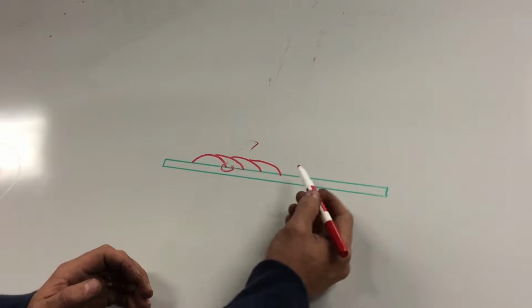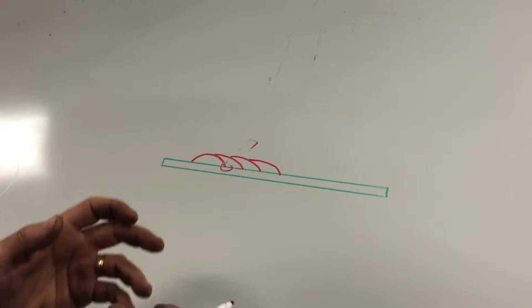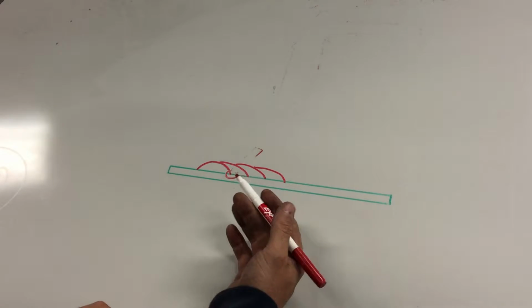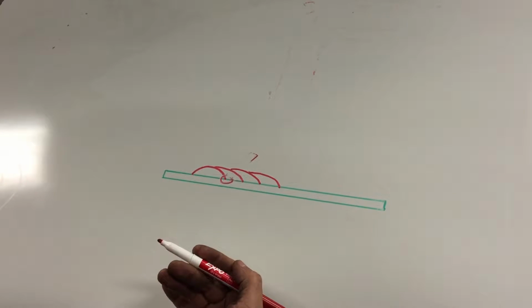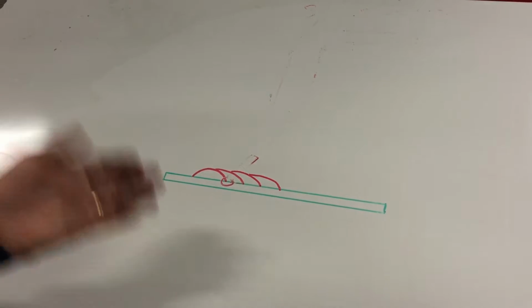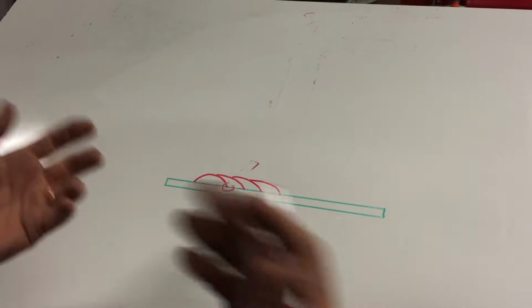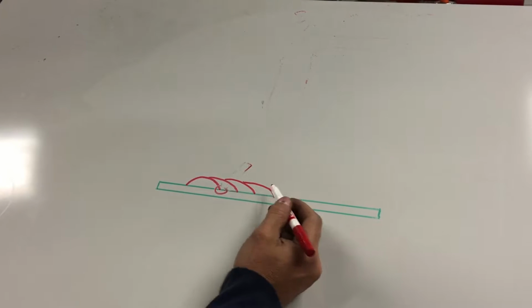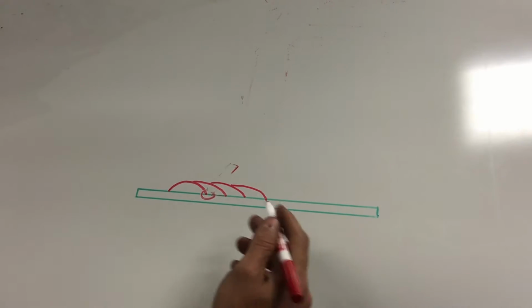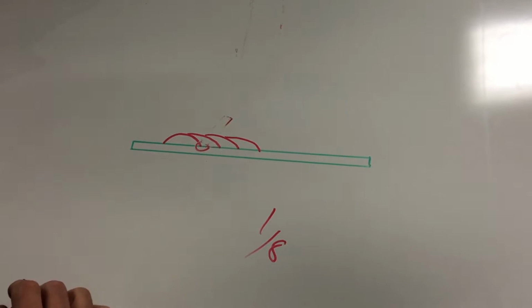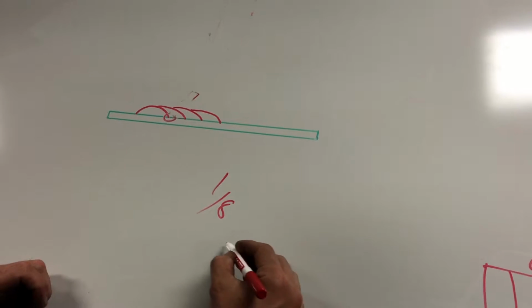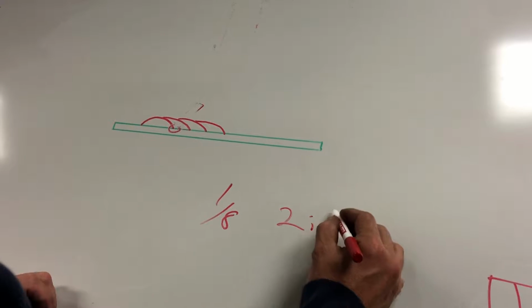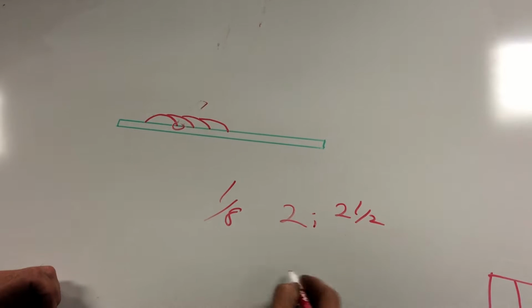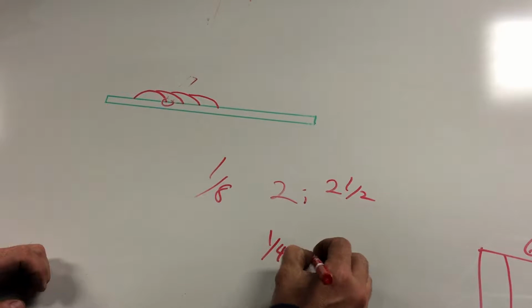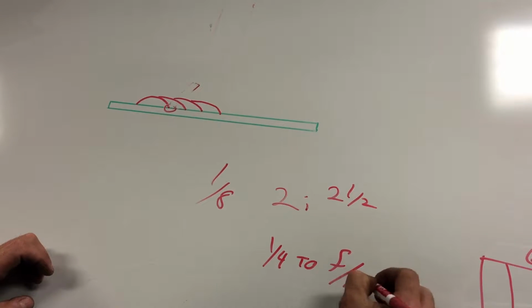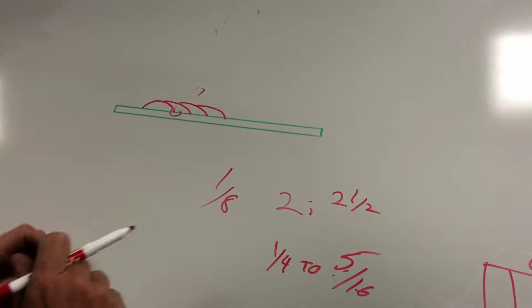The reason I don't suggest doing bigger welds is because of heat affected zone. Multi-pass is proven to be a lot stronger for the fact that you don't overheat the metal per pass. That's another story. We'll talk about that in metallurgy. But we're going to be using a 1/8 welding rod. General rule is your weld should be 2 to 2.5 times the diameter of the rod. So we should end up with a 1/4 to 5/16 weld. So that's what we should end up with.